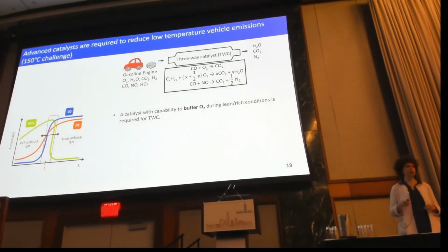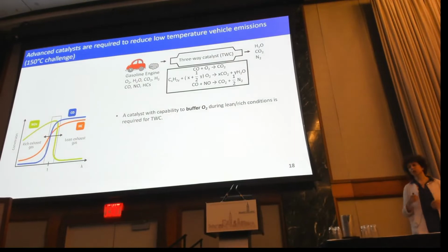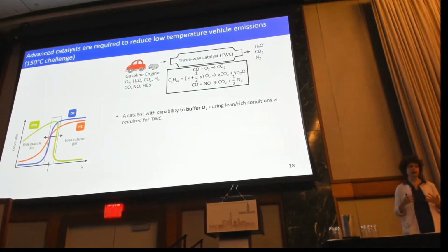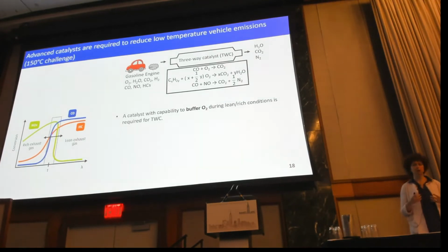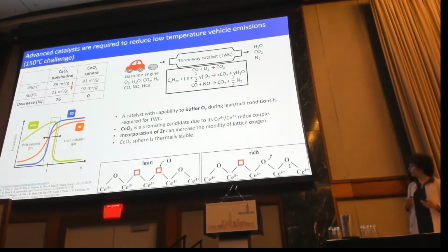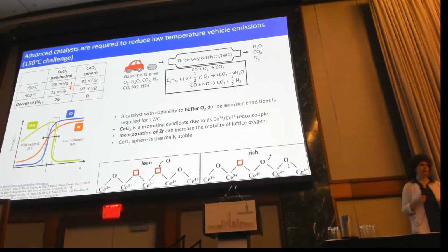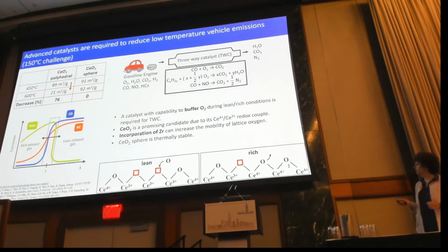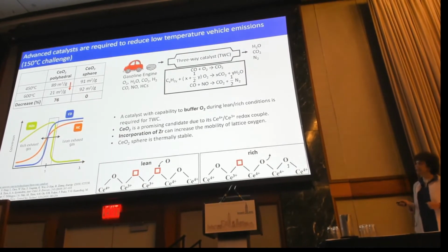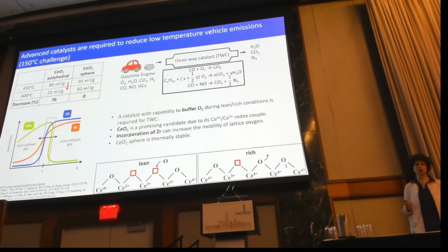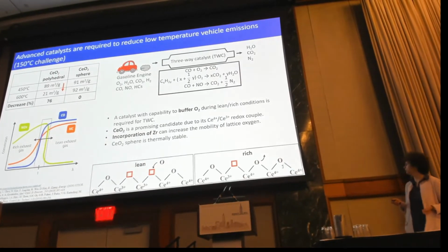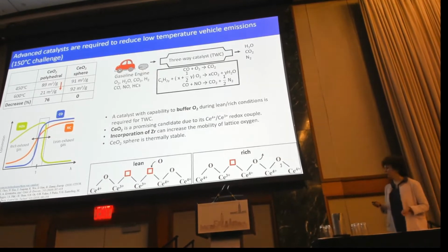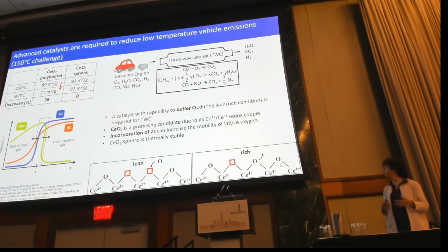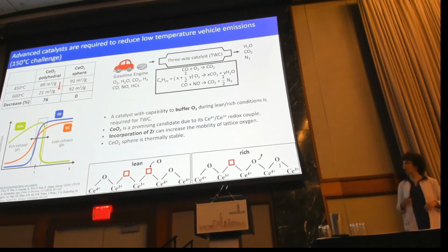However, in realistic conditions, oxygen fluctuates because we go through lean-rich cycles. So it's important to find a material that is able to buffer oxygen. And this material, as it's known, is ceria. Ceria has the ability to store oxygen in its lattice during lean conditions and release oxygen from its lattice during rich conditions. Particularly if we add zirconium onto the ceria, we can even increase the mobility of lattice oxygen.